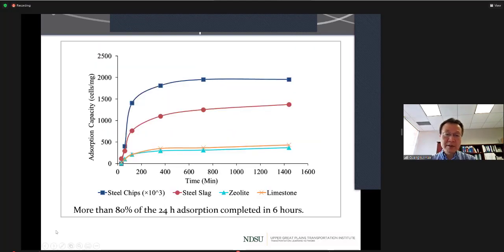So this figure shows the result of the adsorption capacity of the four materials, steel chips, steel slag, zeolite, and the limestone, over a 24-hour adsorption period. And based on this result, we learned that E. coli adsorption to the filter media is a fast process. Based on our results, more than 80% of the 24-hour adsorption capacity can be completed within 6 hours. So we observed fast kinetics for the four materials.